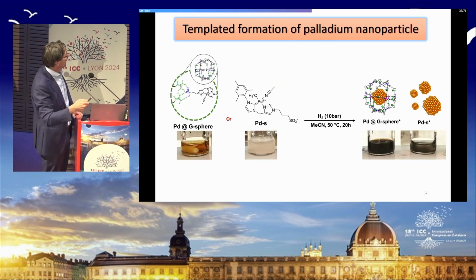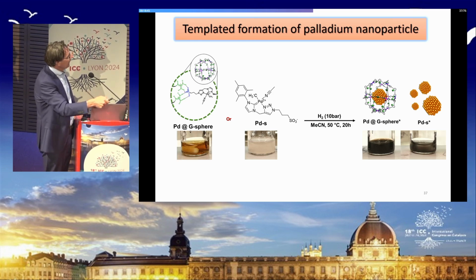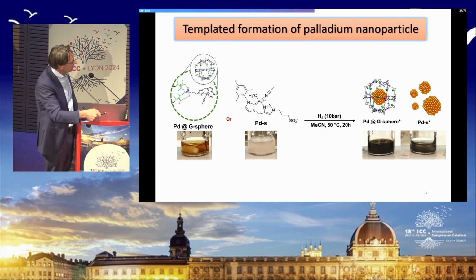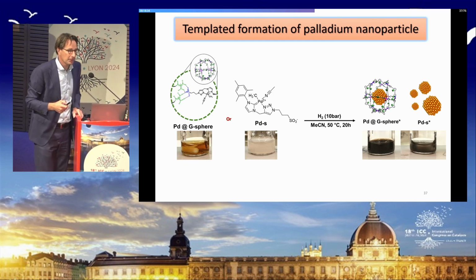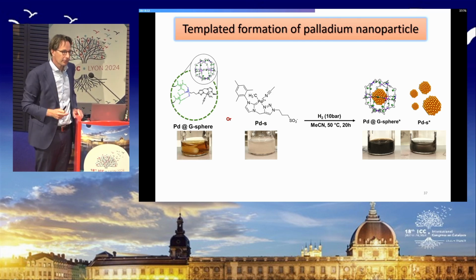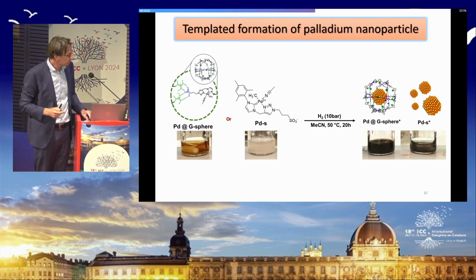So next we looked at the reduction of the palladium complexes that are pre-organized in the nanosphere, and as a control, just a free palladium complex. And at 10 bar of hydrogen in acetonitrile, we form this solution, suggesting that we have palladium nanoparticles, and in absence of this sphere, we see a lot of palladium precipitate, indicating that we have a completely different material.